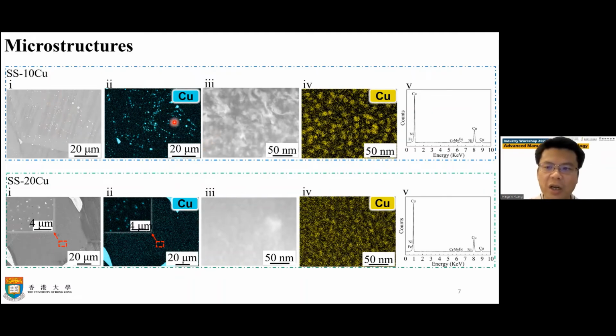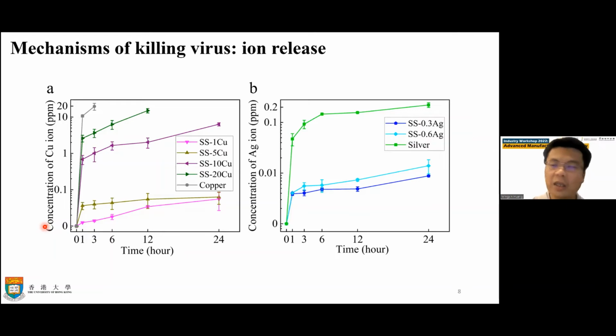So you see also the X-ray. These are EDX. For the EDX, you also see this copper here. So clearly, we have this copper precipitation in this stainless steel. In the normal stainless steel, you do not have these copper precipitations. Okay. For higher copper contents, we are going to see more of this copper precipitation. So basically, we change the microstructure of the steel. And we also check the concentration of the copper ions.